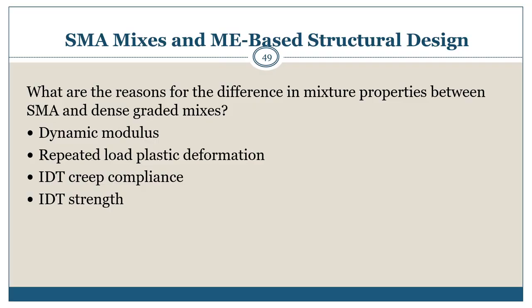Now, what are the reasons for differences in mixture properties between SMA and dense graded mixes? This can be seen in the differences in the test results observed for dynamic modulus, repeated load plastic deformation, indirect tensile creep compliance, and indirect tensile strength as required by mechanistic empirical design procedures. In summary, dynamic modulus values for SMA mixtures can be higher or lower in comparison to conventional dense graded mixtures because the dynamic modulus is measured in accordance with the test procedure in an unconfined state. So the benefit of stone-on-stone contact, or the interparticle friction, is reduced because a test specimen is unconfined.